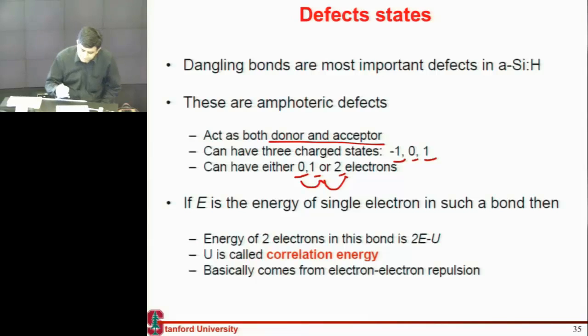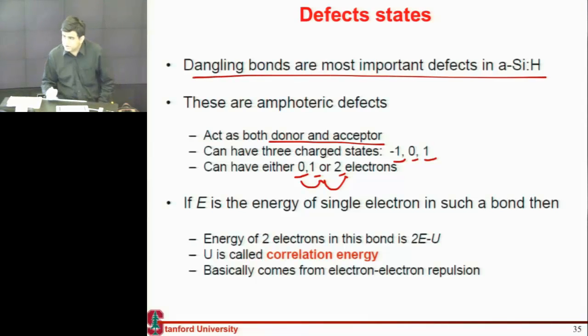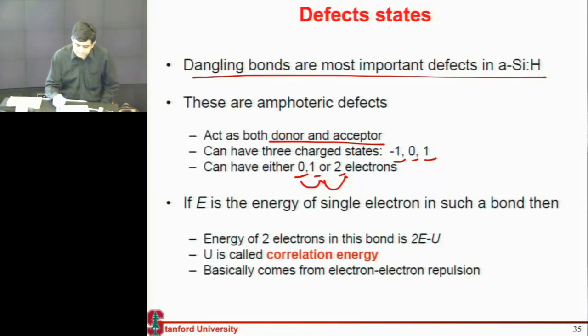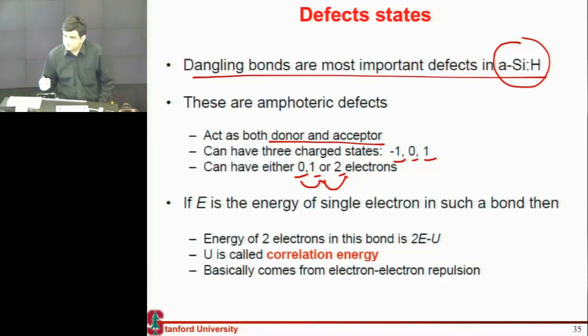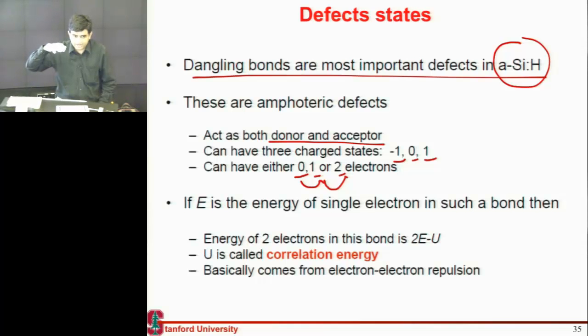So many times people want to avoid this, so they passivate these dangling bonds using things like hydrogen. A very common passivation is to take amorphous silicon and passivate these bonds by annealing it with hydrogen, creating the silicon-hydrogen bond. But it's usually not the strongest of bonds, so when you shine a lot of light on these cells, these bonds tend to break and the efficiency of your solar panel degrades.